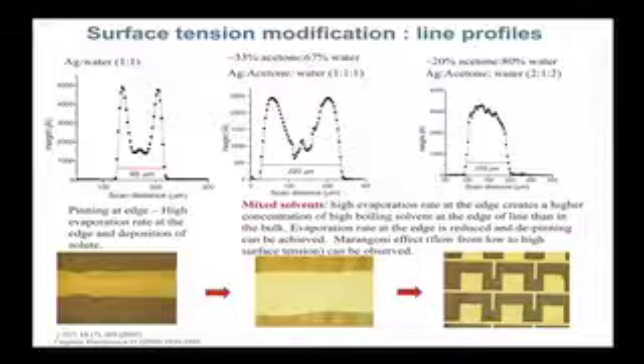So if you look at the profile of this feature, it's terrible. And here there is another problem that comes from the coffee stain effect, which is that the edges of your feature become so thick that you get something that looks like mud. When mud dries, you get all these cracks here at the edge. That's exactly what will happen to a feature if you don't control the surface tension of your liquid, of your ink. So there are things that you can do.